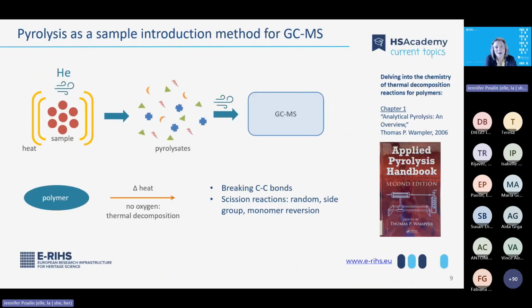Let's have a look at pyrolysis as a sample introduction method. So the sample is heated at a high temperature, over 350 degrees Celsius, and that causes thermal decomposition. The atmosphere is inert. There are no oxidation reactions that can happen. And we see scission reactions instead that can be categorized as random, side group, or monomer reversion. I'd like to point you to this book by Wampler if you're interested in learning more about the different thermal decomposition reactions for different types of polymers. It's a really good resource.